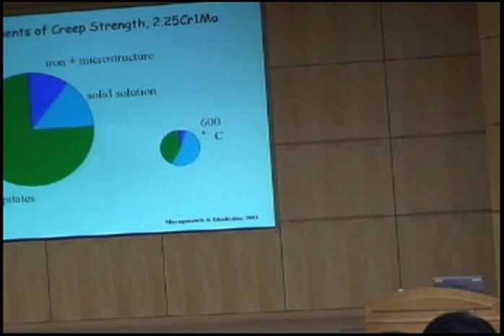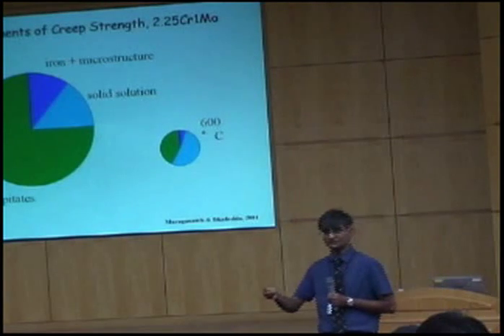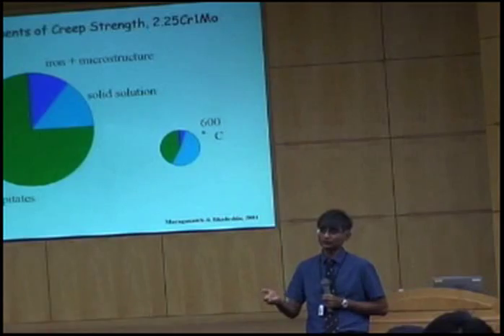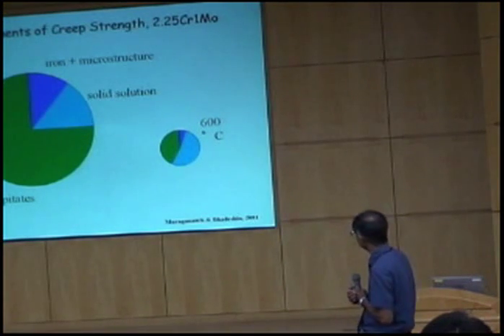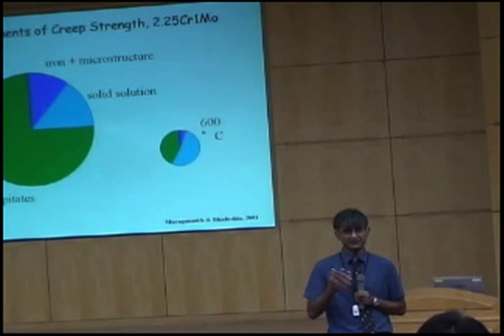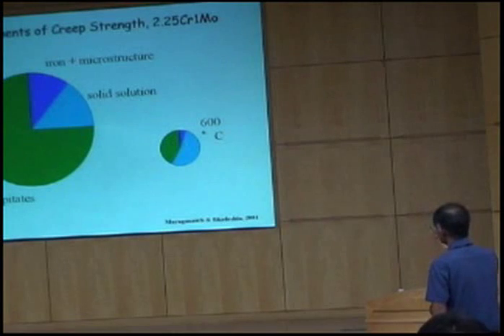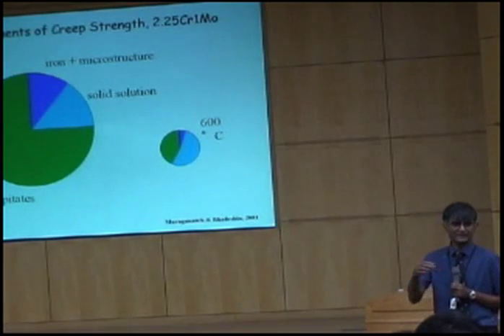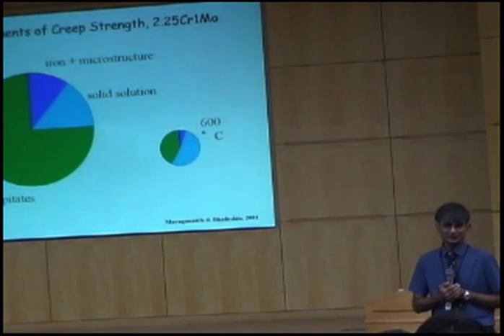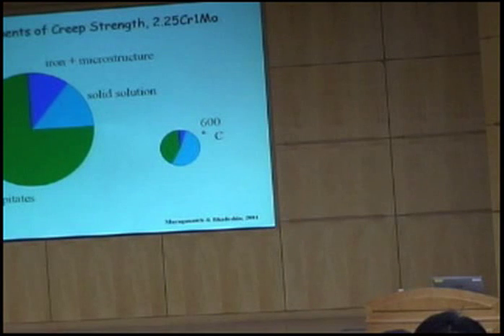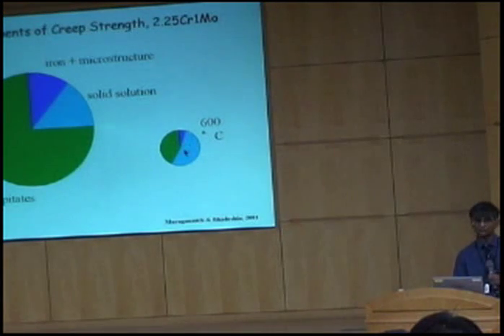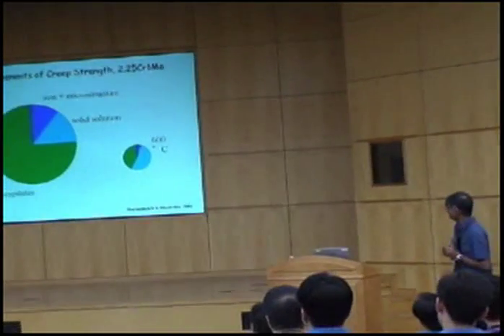Now, of course, temperature comes into this as well, because when we are dealing with creep-resistant bainitic steels, we have to take account of the fact that all the different components change with temperature. And this is a calculation of the creep strength of a classic bainitic steel, 2¼ chrome, 1 molybdenum, which is usually tempered at about 500 degrees centigrade to produce alloy carbides, you know, molybdenum carbides and chromium carbides and so forth. The size of this circle is a measure of the total strength. So obviously, as I go to 600 degrees centigrade, the total strength decreases, because this material is not designed for 600 degrees centigrade. It's designed for about 560 degrees centigrade. So its creep strength drops dramatically as I go to 600 degrees centigrade.